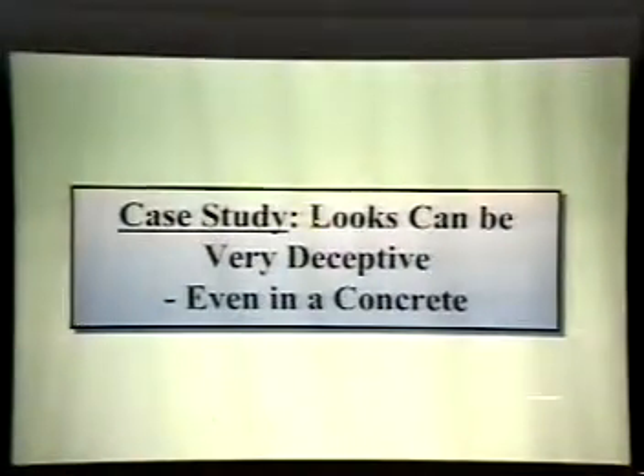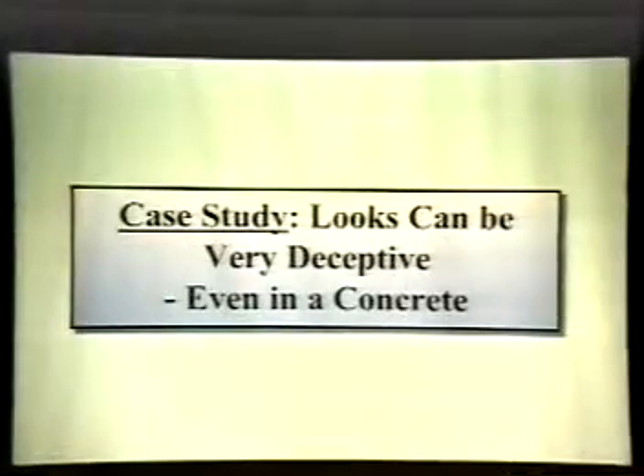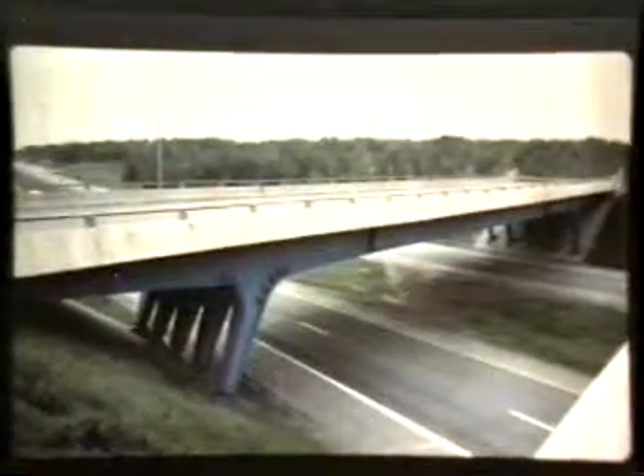Another case study. Looks can be very deceptive even in concrete. A bridge structure, you can see the outside, it's a composite bridge, concrete and steel. Here are the abutments. It looks fine from outside. When we did an inspection of the interior parapets, this is what we saw. Somebody had repaired it at some stage. When we started breaking it, we found it just sort of falling apart everywhere. A closer examination showed quite a network of map cracks in the concrete. We also saw that the expansion joint had closed completely. This was a very worrying factor actually.